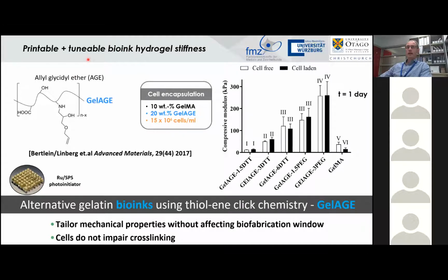If we're then looking at how we can tune hydrogel stiffness, again, the flexibility of the process in terms of being able to modify gel concentration and cross-linker ratios meant that we could get a broad range of different mechanical properties, from quite low, less than 10 kPa, all the way up to around, say, 250. Which meant that we had quite a nice broad range of properties we could achieve that were printable, which you often can't get with GelMA.